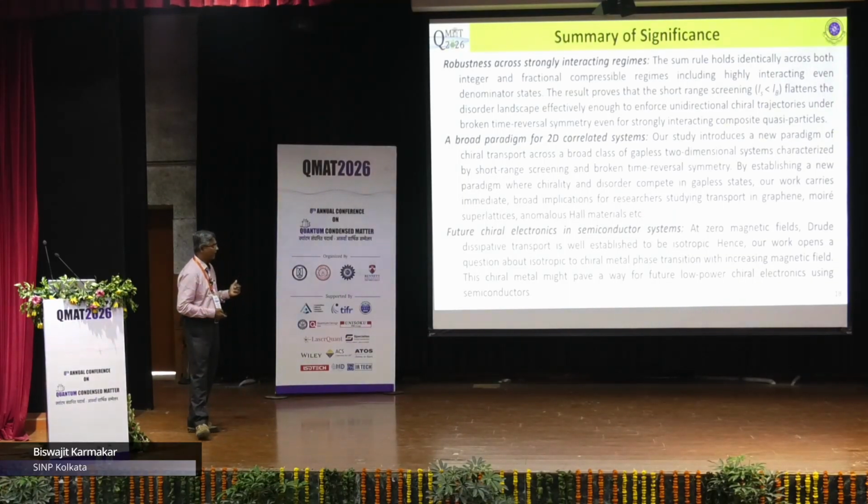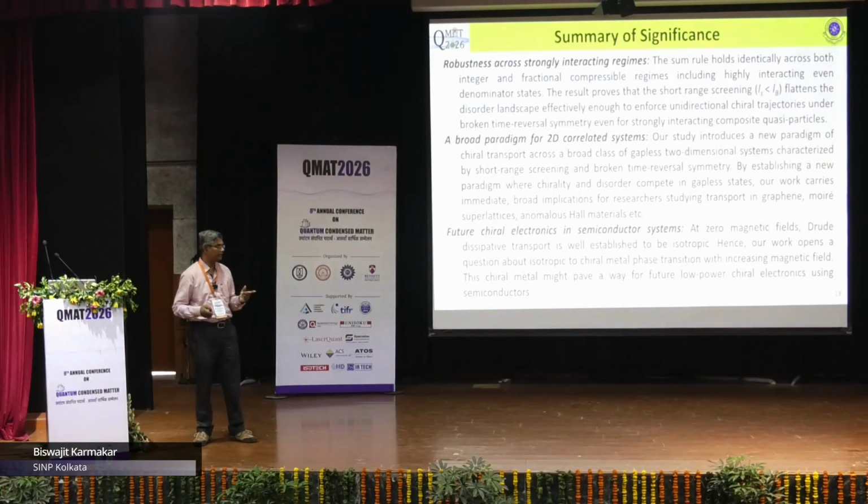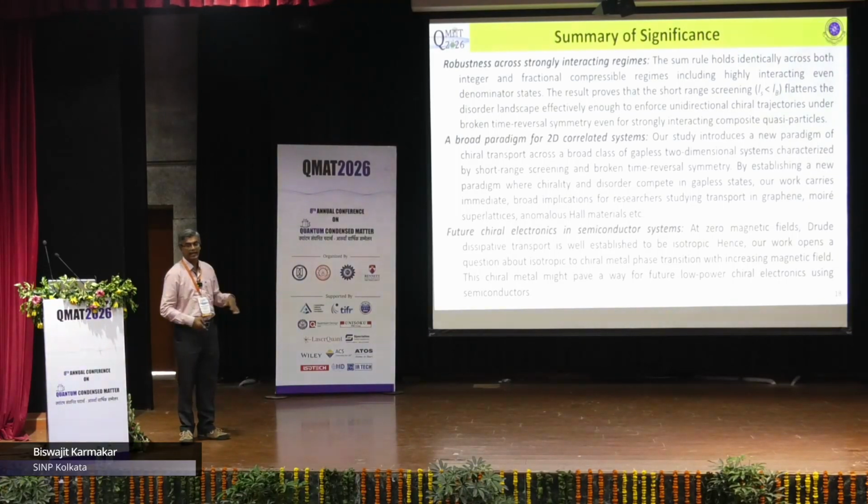Not only that, the screening is not strongly temperature dependent, and the broken time reversal is also not temperature dependent. That's why this chirality can be sustained at temperatures as high as 10 Kelvin.